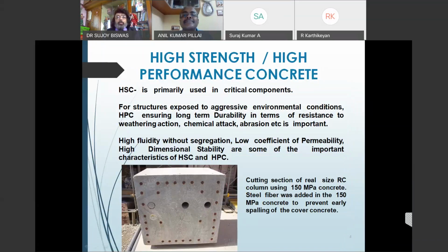The high strength concrete is primarily used in critical components. For structures exposed to aggressive environmental conditions, high performance concrete ensures long-term durability in terms of resistance to weathering action, chemical attack, abrasion, etc. High fluidity without segregation, low coefficient of permeability, and high dimensional stability are some of the characteristics of the high strength or high performance concrete. I've also given a snap of a cutting section of a real size RC column using a 150 MPa concrete. Steel fiber was added in this 150 MPa concrete to prevent early spalling of the concrete cover.